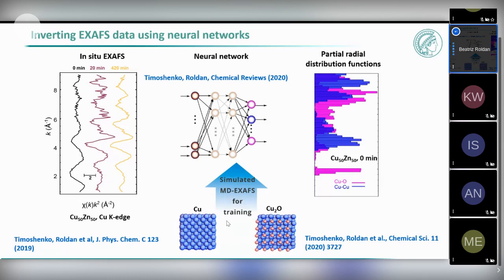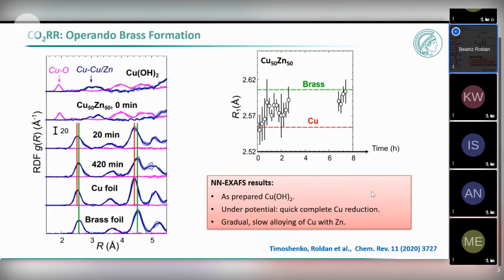We create several structures, in this case thousands of structures, that we use to train this neural network. And using this neural network, we can go from the XAFS spectra to getting the entire radial distribution function of copper-oxygen bonds, for example, or copper-copper bonds, or copper-zinc. We did this here, and you can see that our prepared catalysts contain these copper-oxygen bonds, and then you also have metallic copper.